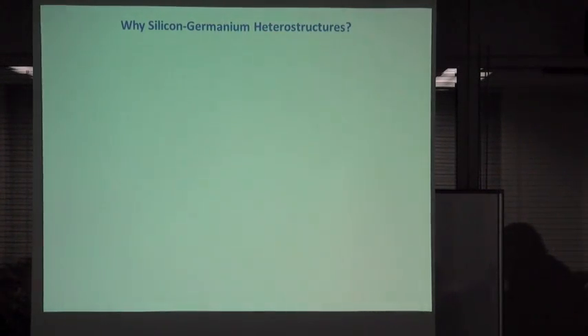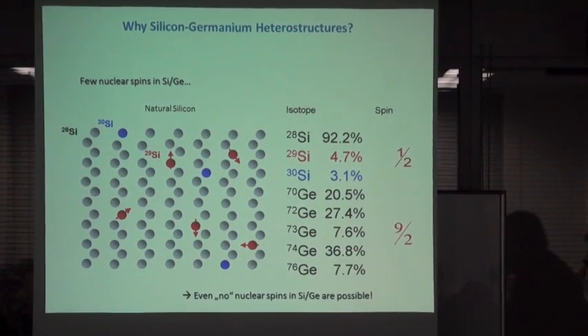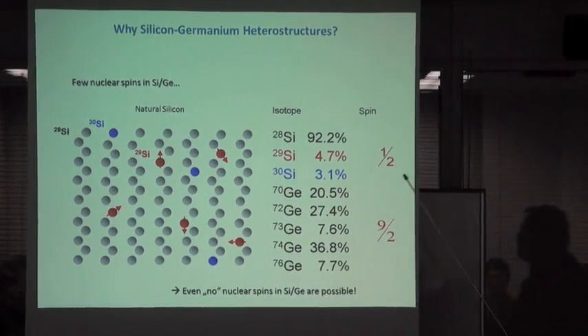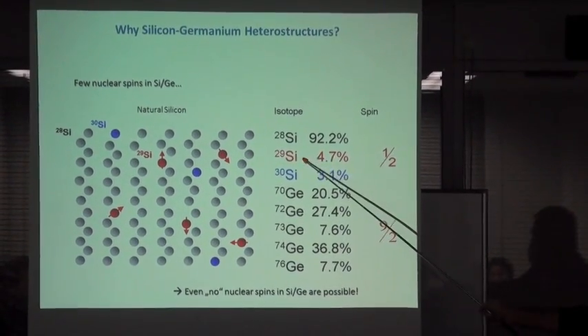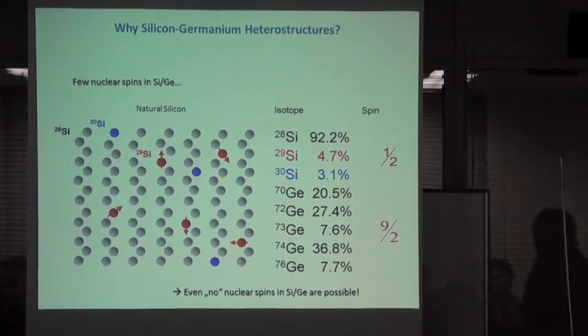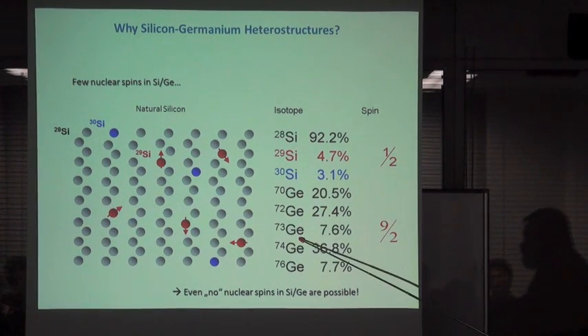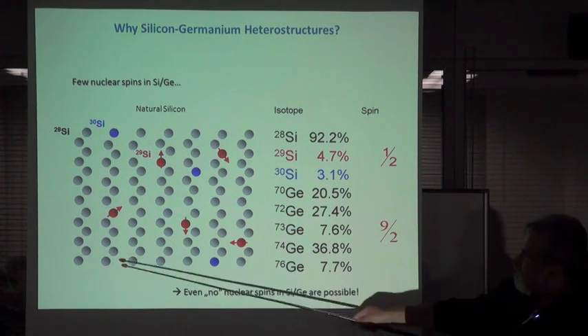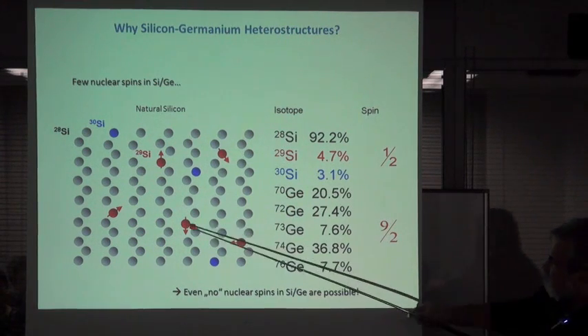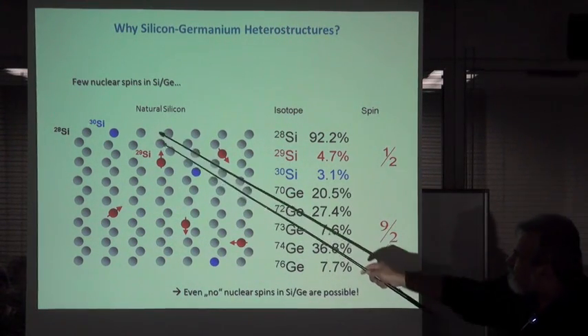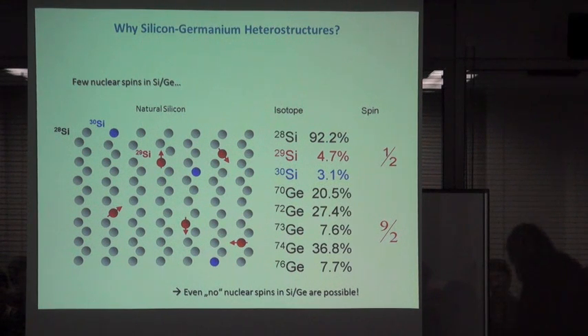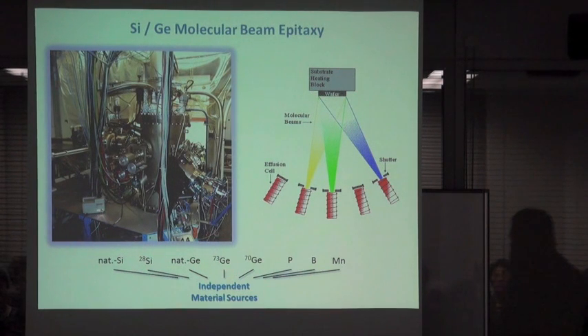So why silicon germanium? I mean, you are working here also in this field. One is that we have very few nuclear spins. Already in natural silicon and germanium, only silicon-29 has a nuclear spin, at about 5%. And in germanium, it's only germanium-73, which has nuclear spin. And actually, this is a schematic. These are about 100 atoms. And so you have 5 nuclear spins and a few silicon-30, which have no nuclear spin also in the system. But you can also grow with isotope clean materials, and you actually can also avoid silicon-29 spins or still make it lower. So there may be much longer coherence times.